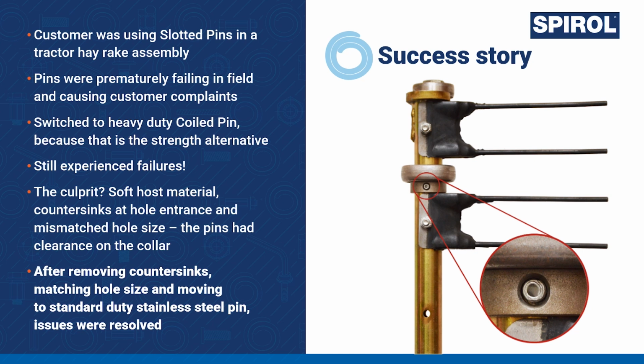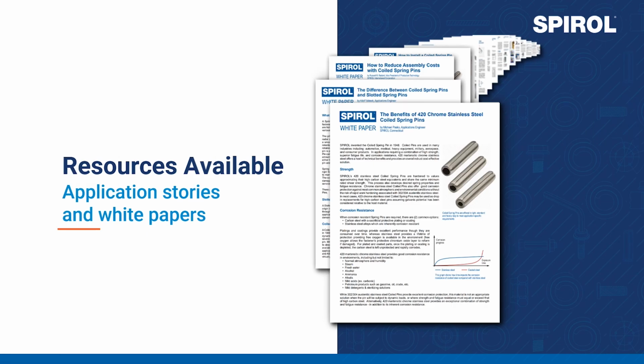So therefore, in addition to changing to a standard duty coiled pin versus a heavy duty slotted or coiled pin, SPIROL recommended that the hay rake manufacturer change from a zinc plated high carbon steel pin to a plain 420 martensitic stainless steel. The 420 stainless provides great corrosion resistance in this application without any need for subsequent coating or plating. And as we have established, 420 stainless has superb fatigue resistance in dynamic applications.